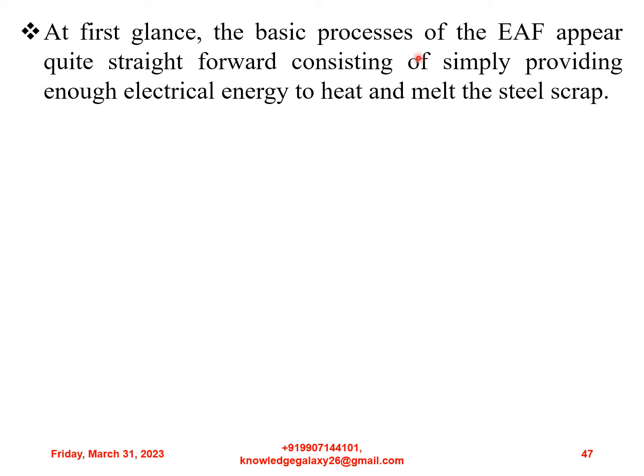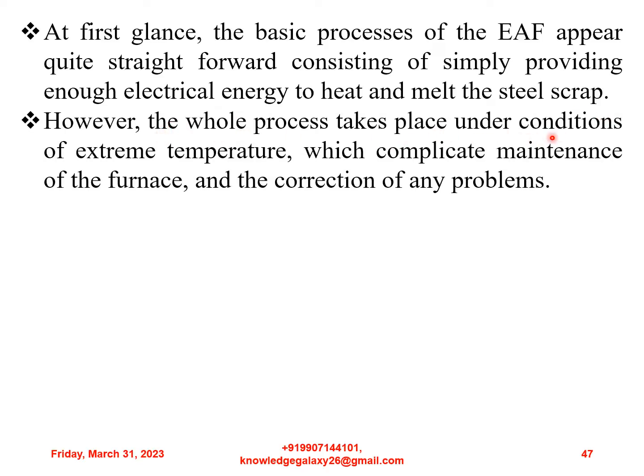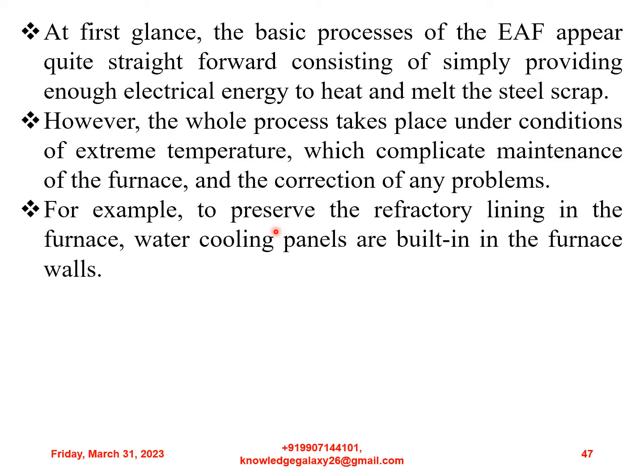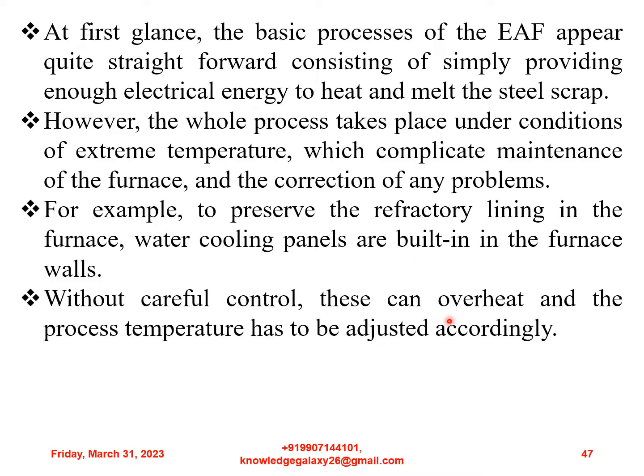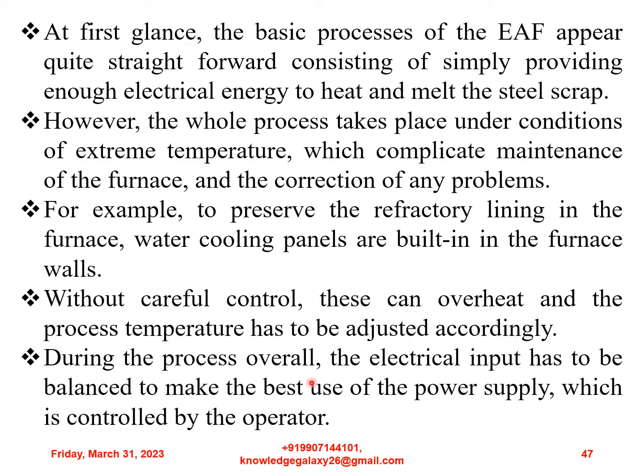At first glance, the basic processes of the electric arc furnace appear quite straightforward, consisting of simply providing enough electrical energy to heat and melt the steel scrap. However, the whole process takes place under conditions of extreme temperature, which complicate maintenance of the furnace and the correction of any problems. For example, to preserve the refractory lining in the furnace, water cooling panels are built in the furnace walls. Without careful control, these can overheat and the process temperature has to be adjusted accordingly. During the process overall, the electrical input has to be balanced to make the best use of the power supply, which is controlled by the operator.